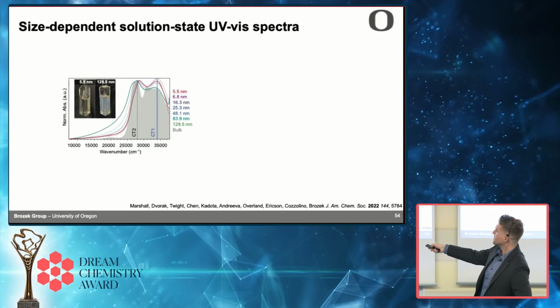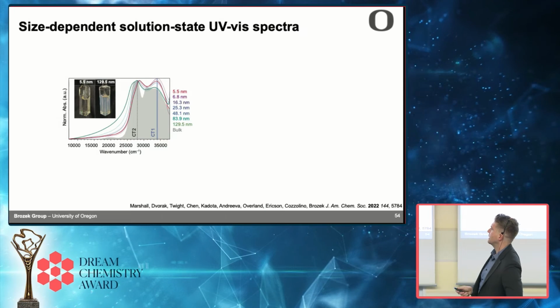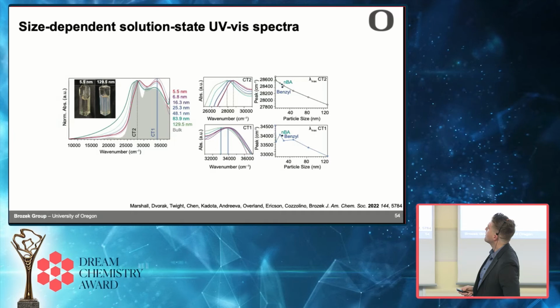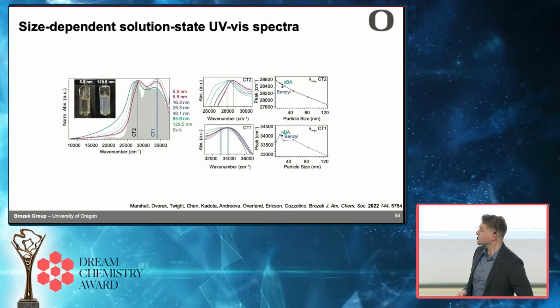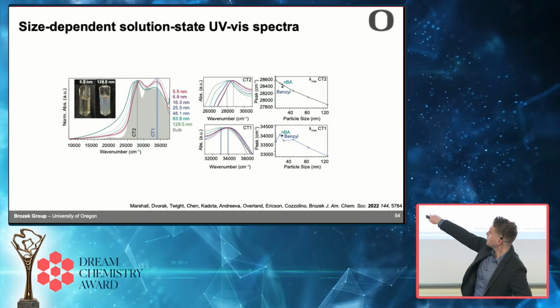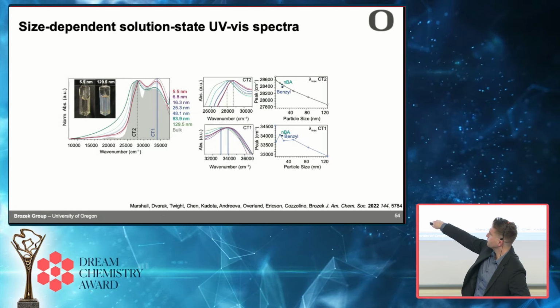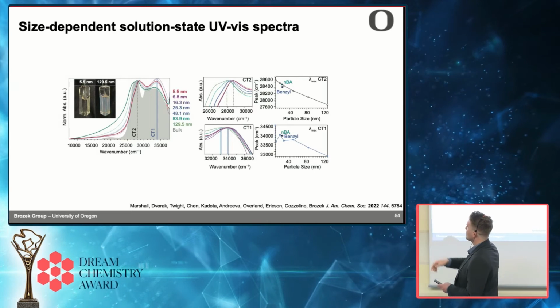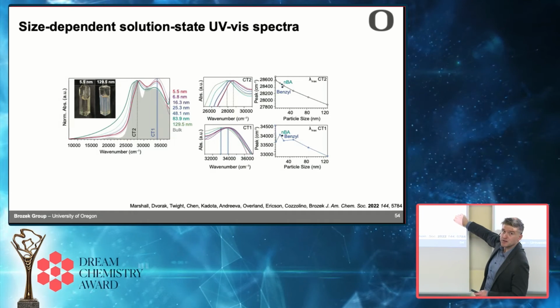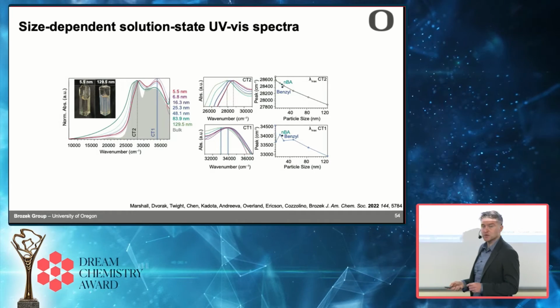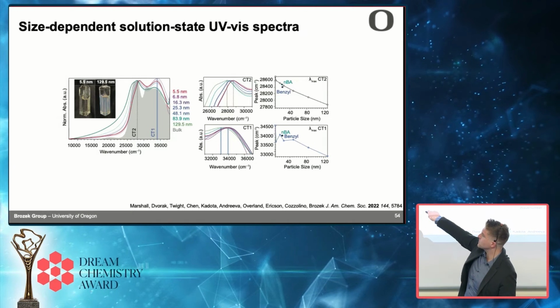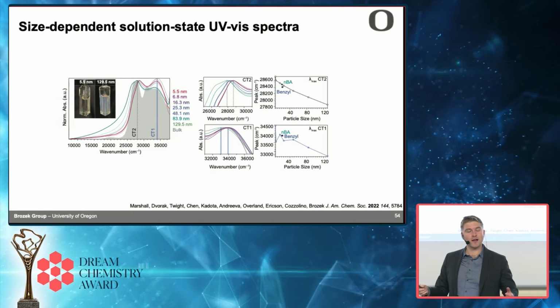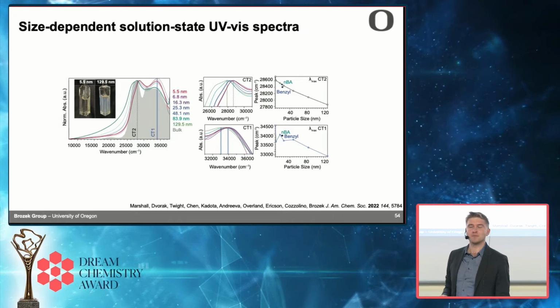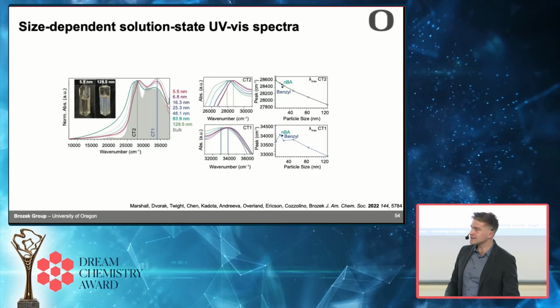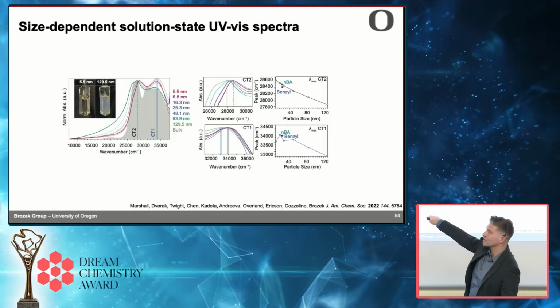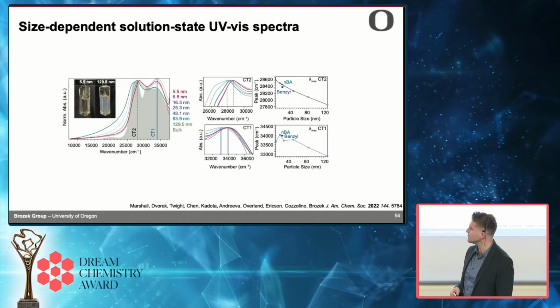These are metal ligand charge transfer bands. If you look really closely at these two bands, something unexpected happens. They're size dependent. Here's the peak position of those two bands. In fact, if you were to include the position for the bulk material, it would be way out here somewhere. So in other words, as you make the particles smaller, the position blue shifts and moves to higher energy. So of course I thought, oh my God, are we seeing quantum confinement in something that isn't just cadmium selenide? Well, the way to test that idea is you try to fit this to a 1 over radius or 1 over radius squared, and it doesn't fit.